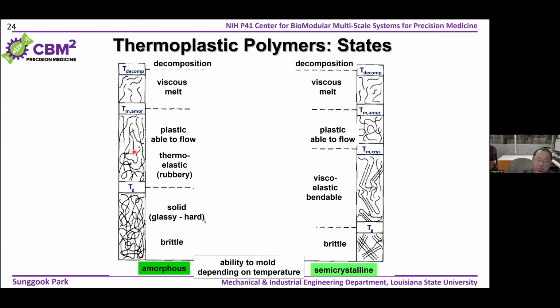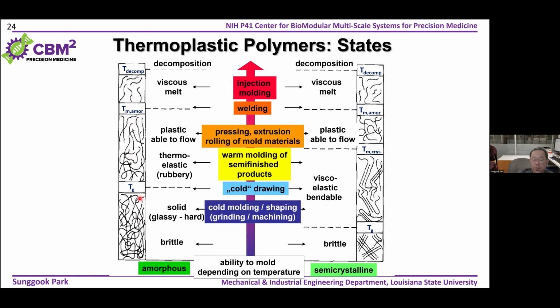And if you increase the temperature further, you reach the melting temperature. Once you pass this melting temperature, you have a viscous melt. So depending on the temperature regime, you have different applications. At low temperature, you have cold molding or shaping, but most nanoimprint lithography is done around 30 to 50 degrees C above the Tg. And injection molding is performed above the melting temperature of the polymers, at the viscous melt state.